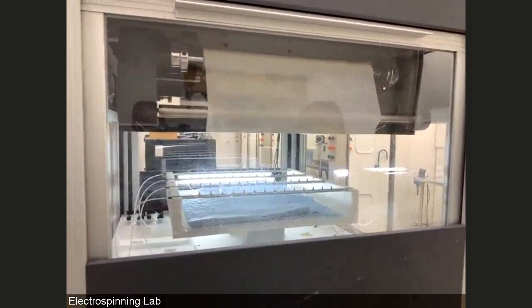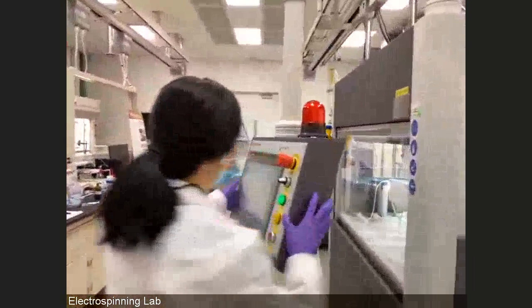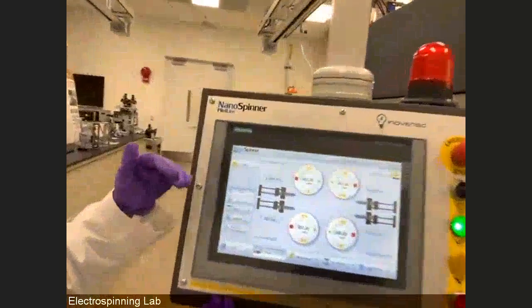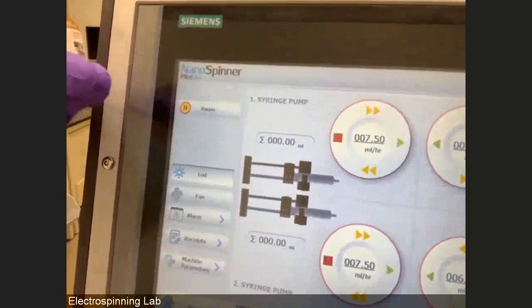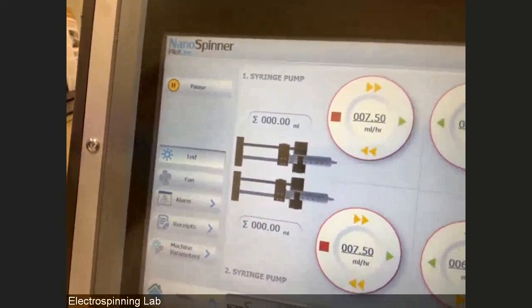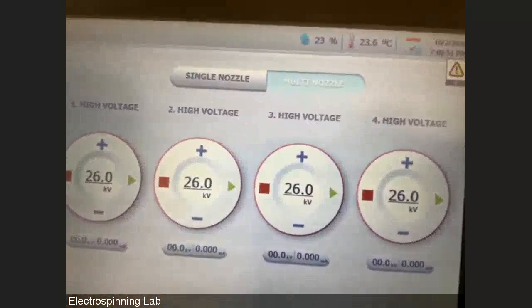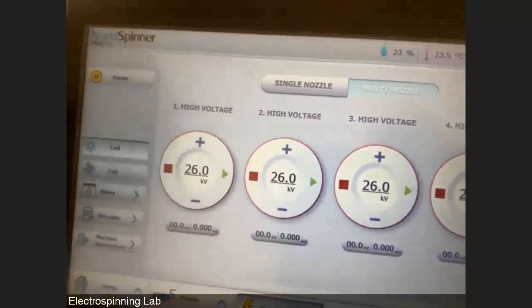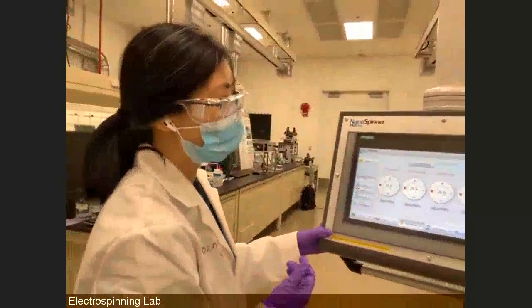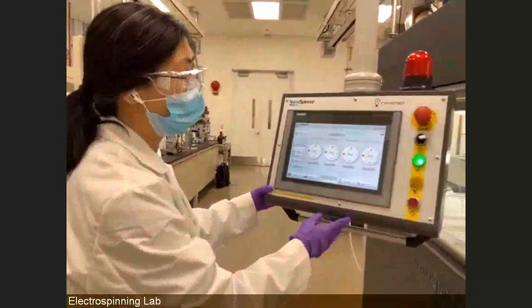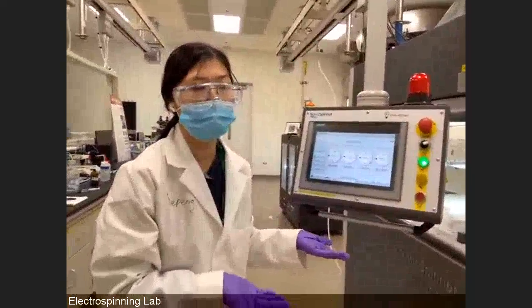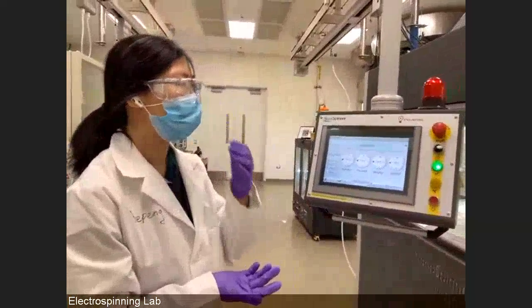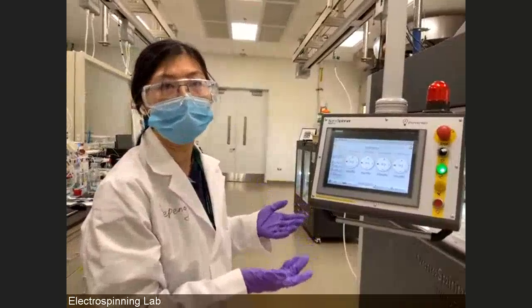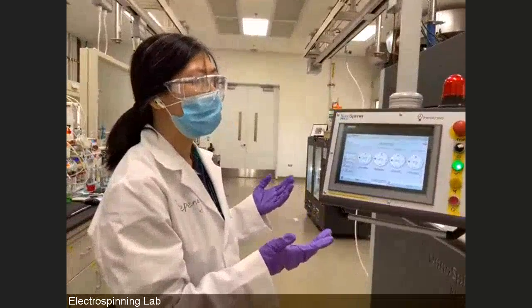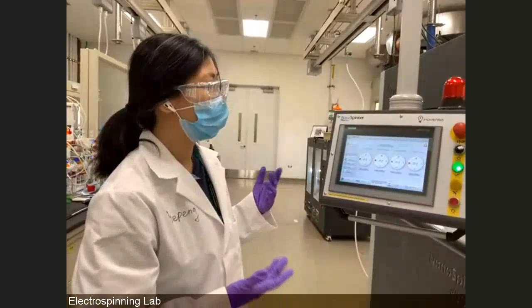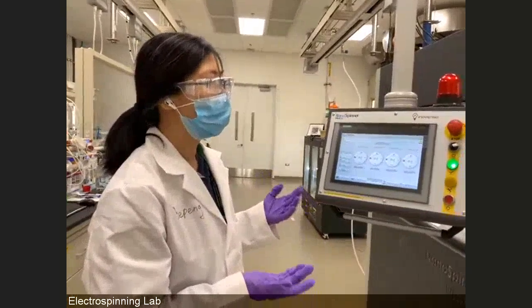For the other parameters that you want to adjust, you can see from the control panel that you can adjust the injection rate of the solution, and you can also adjust the voltage, like here. The interaction of all these parameters gives you the optimization of fibers. So you can see that when you introduce multiple nozzles, it's actually quite complex. There are several challenges. One is crosstalk between the nozzles, which makes the electric field distribution very complex. Sometimes you even need simulation to understand the effect.